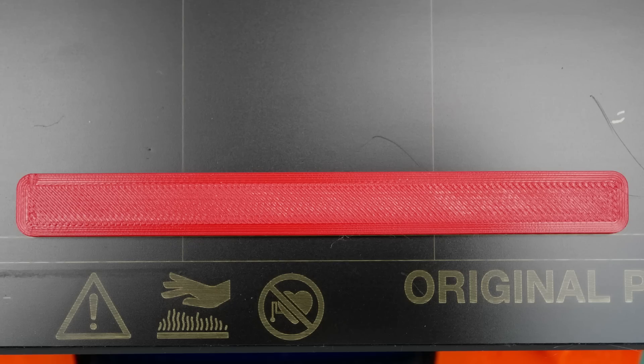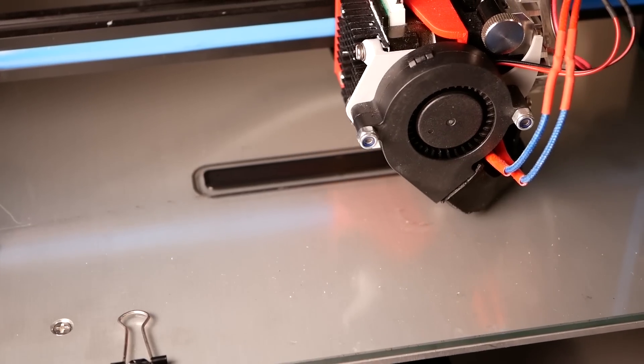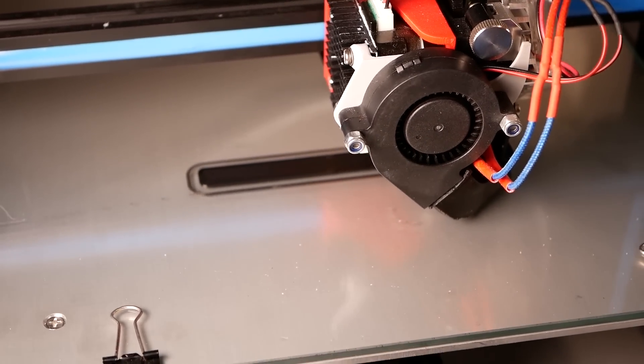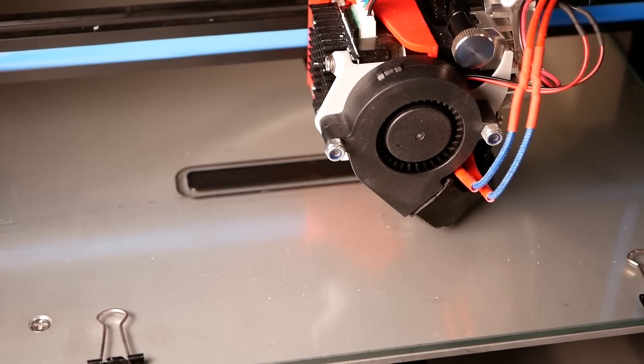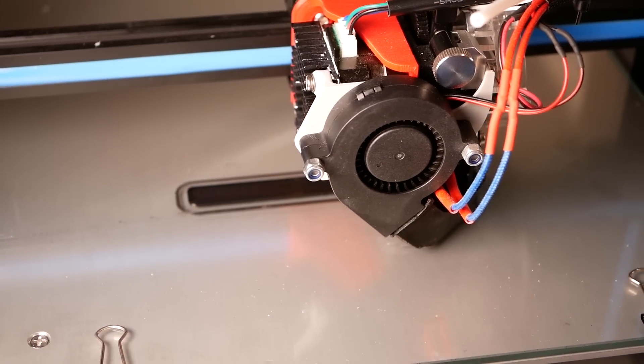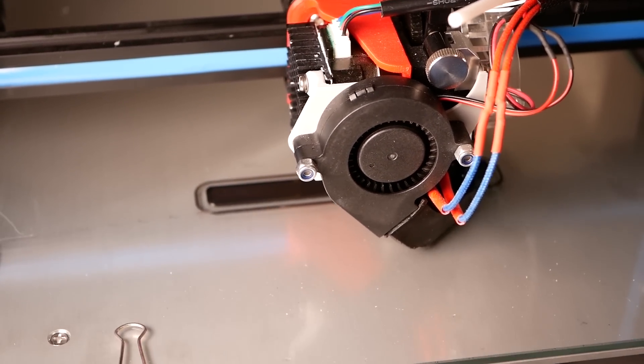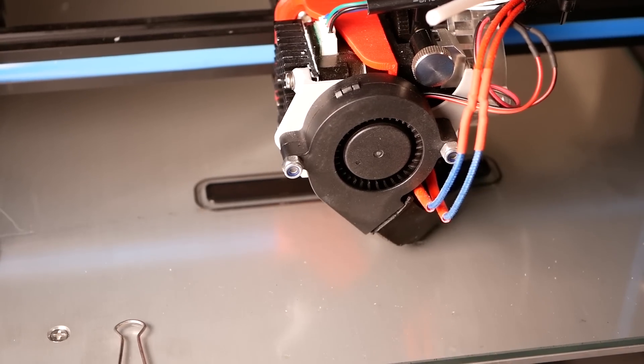The sample itself is a simple bar that is 120mm long, 12mm wide and 4mm high. All of the samples were printed on my CR10 with a Titan Aero Extruder and a 0.4mm nozzle at 0.2mm layer height, 5 perimeters and 100% infill. All of the CAD files are by the way available on Thingiverse if you want to build one your own.